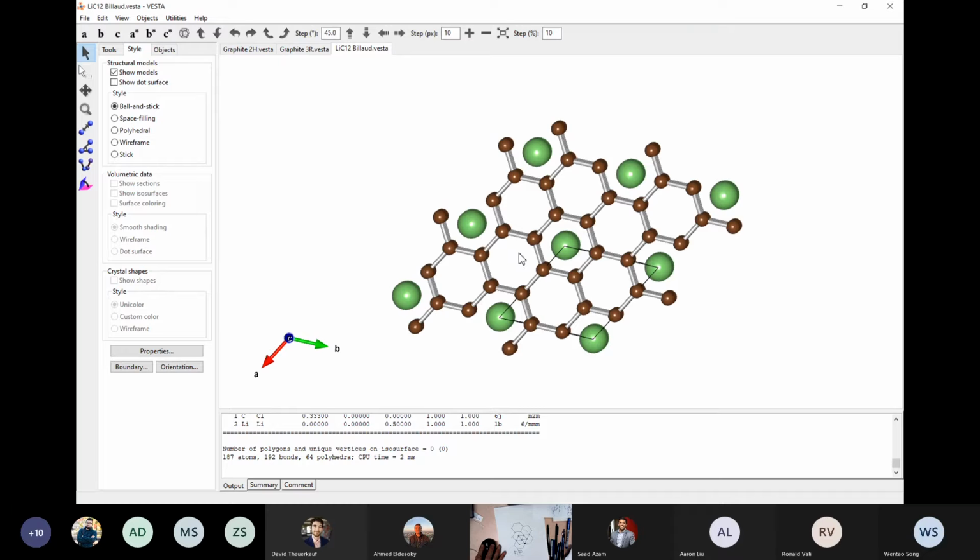And it just takes too much energy to put them close together. And what you learn is the lithium would rather electroplate on the surface as compared to filling near neighbor sites. It's just more energetically favorable to plate lithium on the surface compared to fill near neighbor sites because of the large Coulomb repulsion that's present.